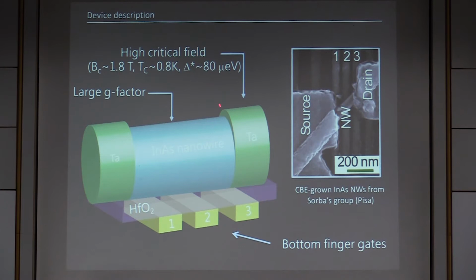Another ingredient that we have is we use tantalum superconductors, that was mentioned by Sébastien. Tantalum is a material that exhibits a superconducting transition. Actually, there are two phases. One of them has a superconducting transition a bit below a Kelvin, and the gap is around 80 microelectronvolt, and this is the one that we end up having. You can have a phase with a 4 Kelvin transition, and what is interesting is that the critical field is very large. It is 1.8 Tesla, and that is because tantalum is a very heavy metal with strong spin-orbit coupling, so it's quite hard to kill the superconductivity despite the small energy gap.